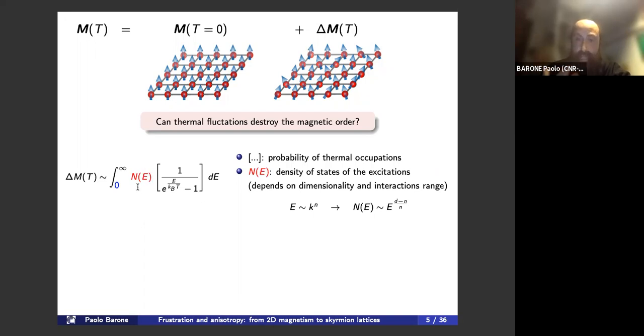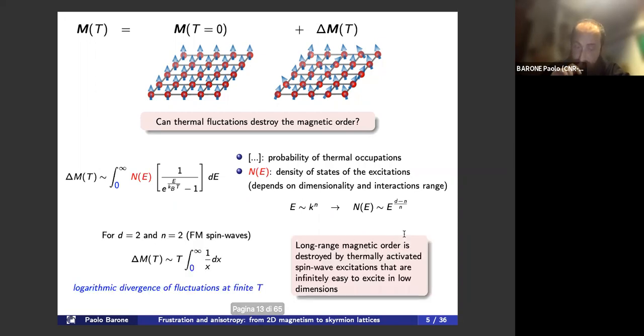And of course, what is crucial here is that the density of states depends on the dimensionality of the system, and also on the interaction range. Basically, if you assume that the excitation spectrum can be written as a power law with a power of n, then it's easy to show that the density of states scales with a power law with the power (dimensionality minus n) divided by n. For ferromagnetic spin waves, one immediately realizes that this density of states becomes a constant, and then by expanding the Bose-Einstein probability function, one sees that the thermal fluctuations show a logarithmic divergence at any finite temperature. That basically means that such spin wave excitations are so easy to excite in two dimensions that they immediately destroy the long-range order.